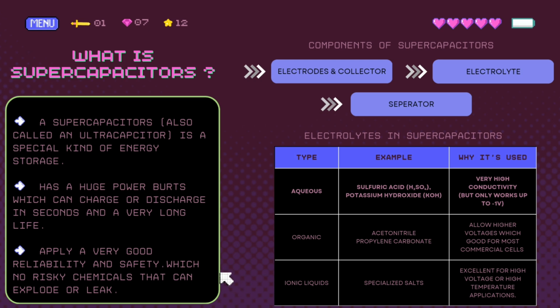Next, let's deep dive into the electrolyte part. We include three types of electrolyte, which are aqueous electrolyte, organic electrolyte, and ionic liquid electrolyte. Aqueous electrolytes such as H2SO4 and KOH offer very high conductivity but are limited to about 1 V per cell. Organic electrolytes such as acetonitrile and propylene carbonate support higher voltage, which means better energy density for commercial cells. And last but not least, we have ionic liquids, which are specialized salts, excellent for high voltage and high temperature environments, which can also be said as an electrolyte that's stable for harsh conditions. We move to the next slide.